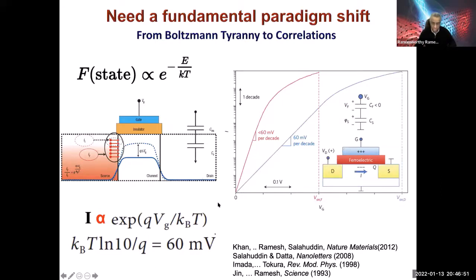Okay, that 60 millivolt per decade is shown here in the blue curve. That's in the ideal case. In real transistors, it could be worse than 60. Typically, it's about 80 millivolts per decade. Okay. Therefore, if you want to make a switch out of it, you need 6 orders of magnitude change in the behavior, so you know what kind of voltage is needed. That automatically tells you that you're going to be limited somewhere in the 800 millivolt kind of range. And that's where CMOS is today.